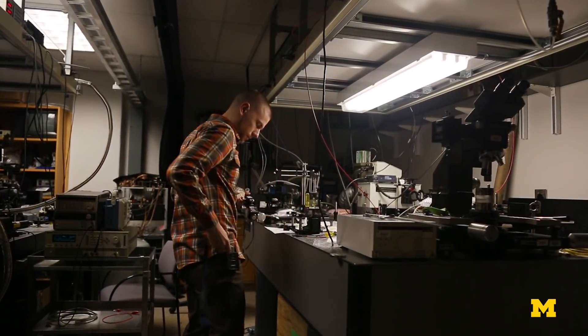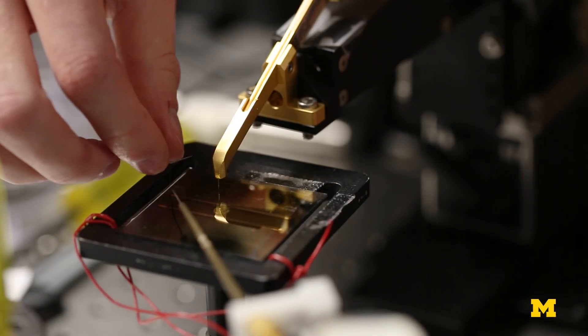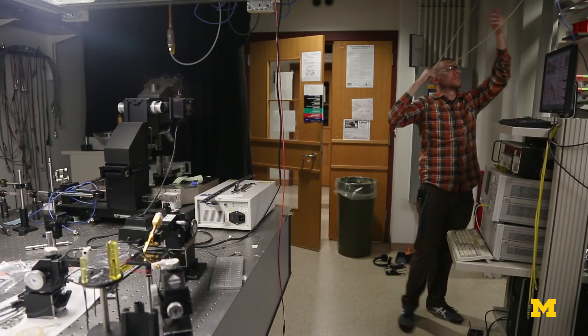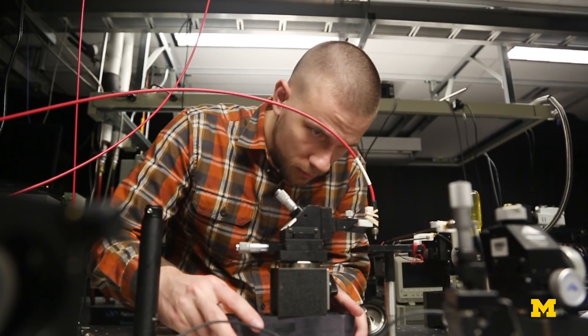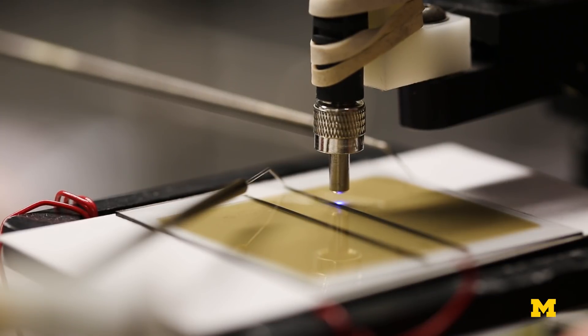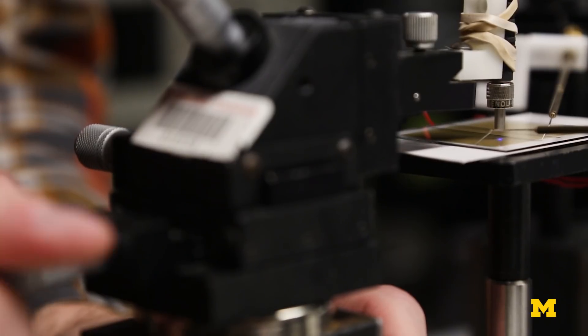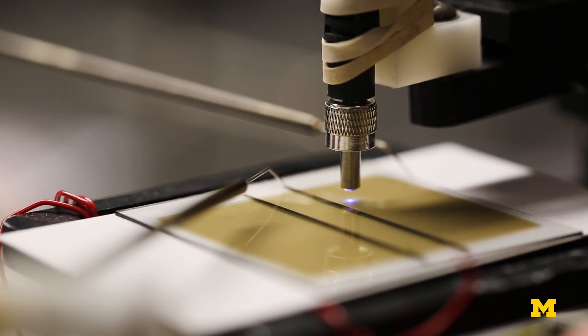We made a structure in an organic solar cell that we thought was an ordinary structure, but it wasn't. And then we were paying attention. What we found is that if you originate a charge a long distance from the detection point in an organic, it can still be detected with high efficiency. The electrons just keep going over very long distances.